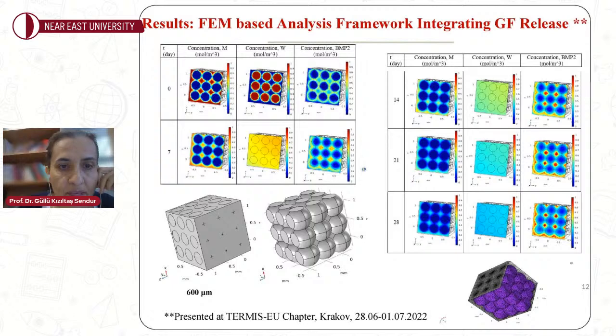And the BMP concentration growth factor release is, as expected, following a release that increases in time initially and then degrades over time, as was predicted by the reference study in Sun back in 2013 and validated recently.